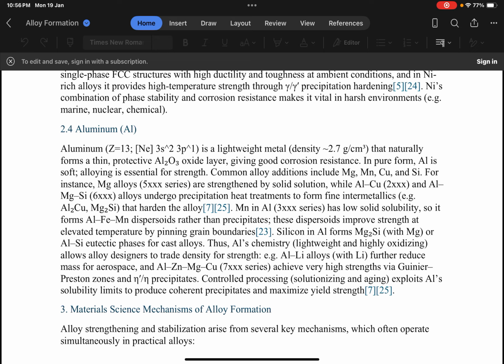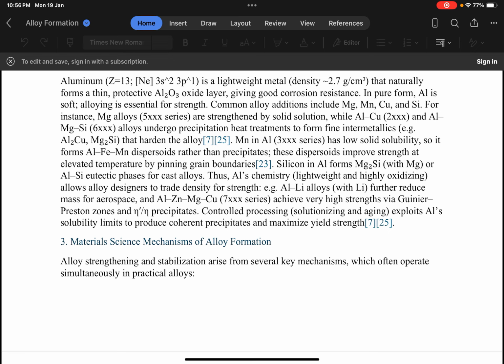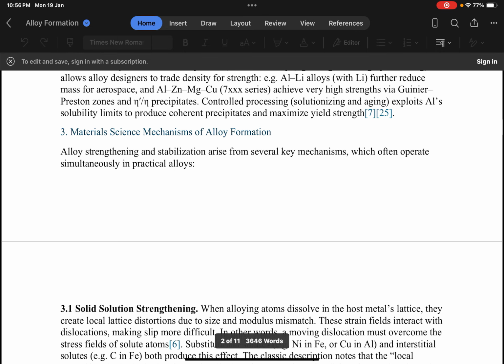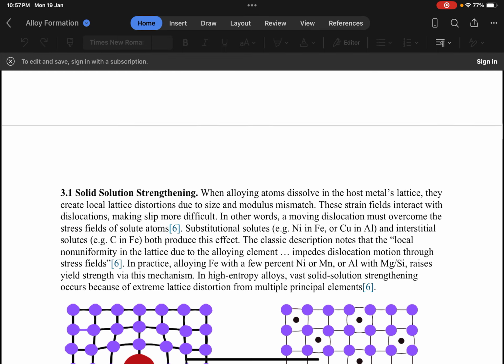In precipitation hardened aluminium alloys, heat treatment produces fine intermetallic particles that strongly resist dislocation motion. This balance of low density and high strength makes aluminium alloys ideal for transportation and aerospace structures. Now I will discuss the key strengthening mechanisms. Alloy strengthening and stabilization arise from several key mechanisms which often operate simultaneously in practical alloys.